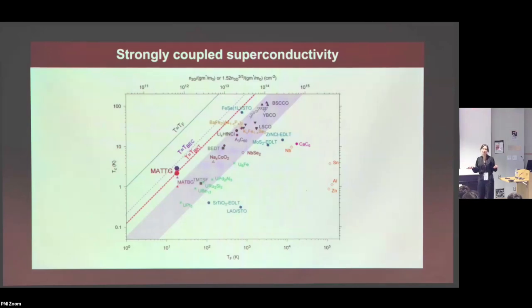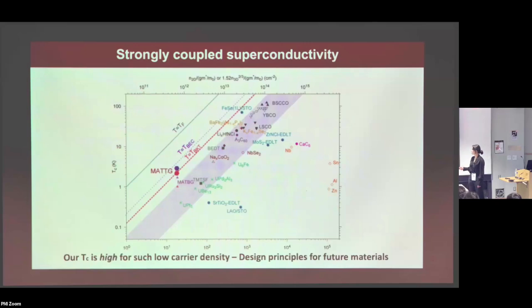So that's cool, but why would you care about strongly coupled superconductors at all, right? Other than the fact that maybe it's kind of exotic. I think you can understand it in a way that, even though our TC is only like 2 Kelvin, 3 Kelvin order, so it's not actually that high, especially compared to the actual high TC superconductors. But what this high ratio tells you is that our TC is actually very high for having such low carrier density in the system. We have almost atomically thin superconductivity.